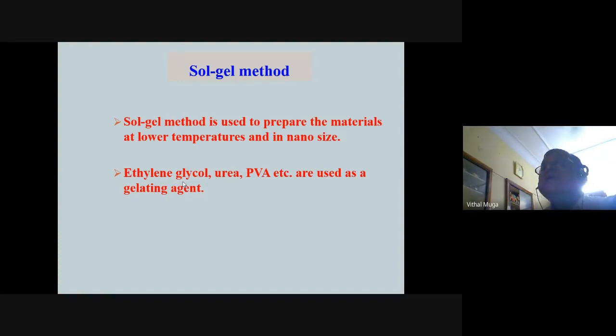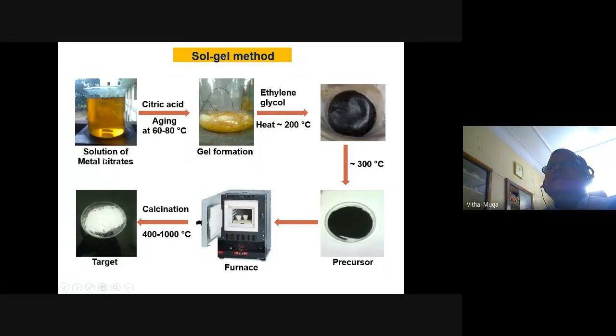So what we do is take the materials. I think I have a slide. You take metal nitrate solutions, and then we add citric acid because this is a very good ligand, and then we age it, and then we add ethylene glycol, and then once again you heat it, then it becomes a porous solid, a black mass. Now this black color appears because ethylene glycol is a carbon compound, and when you heat a carbon compound, it becomes black because it is reduced, and subsequently it will be oxidized. Then slowly we heat it, we get a precursor, and then you put it in a furnace and heat it, and we will get the desired materials.